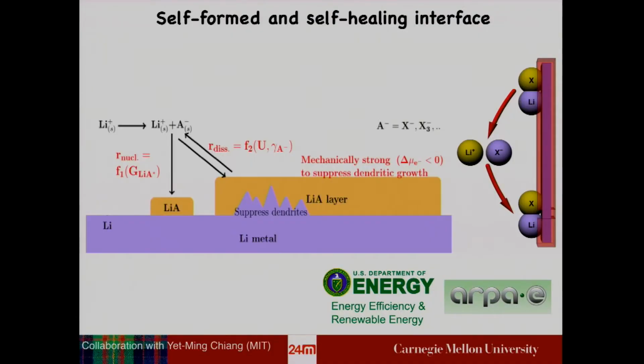Now, there's a second part that's required to enable lithium metal anodes, which is that as you cycle these batteries, this barrier film will invariably crack. And so we need some mechanism to close this crack. And so that's the self-healing part of our scheme, which is essentially to add some constituents in the liquid electrolyte that will immediately close the film once a crack develops. And so we think with this self-formed and self-healed approach, we can enable a lithium metal anode.